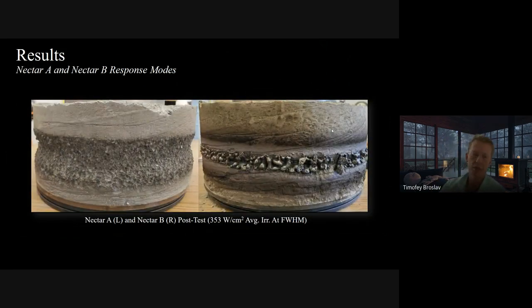Seen here are the simulant cakes from Nectar A and Nectar B at the same irradiance. You can see, of course, Nectar B melted significantly, and this is because it did not have what's called unheated vermiculite. So vermiculite was one of these minerals used in making the simulant. For a later simulant for Nectar B, we accidentally purchased vermiculite that was already preheated, so it didn't really undergo this huge expansion step once heated, because it already happened to it.